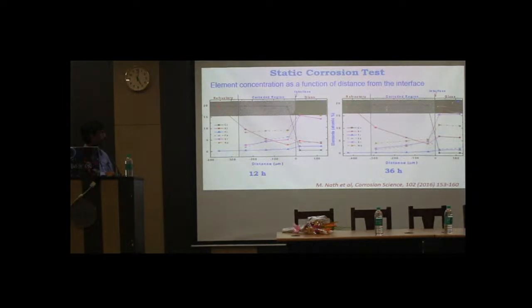And the glass portion also contains some amount of aluminium. That means in the uncorroded region aluminium is there, and the aluminium concentration decreases as it moves towards the glass. That means the aluminium is only leaching out from the refractory to the glass. Another interesting thing is the silicon and sodium, as I mentioned; it will enter, because this borosilicate glass also contains some sodium and silicon. But the iron oxide also enters into that. Suppose the iron oxide may be present in the glass or maybe in the crystal structure.